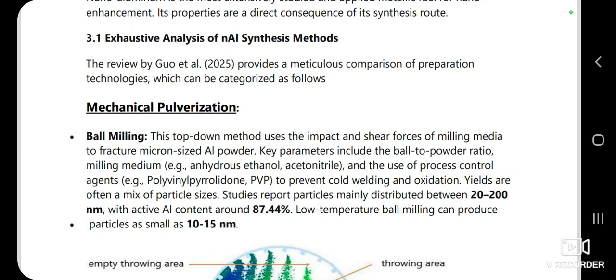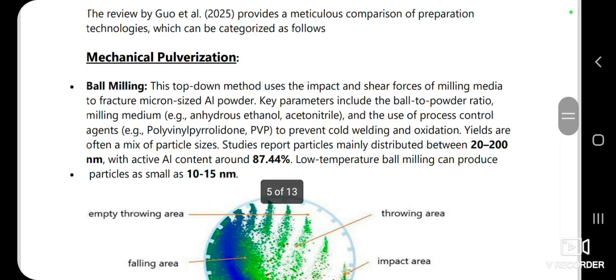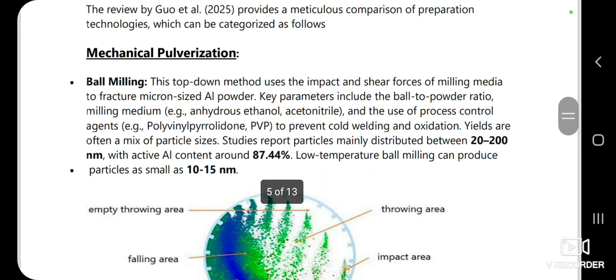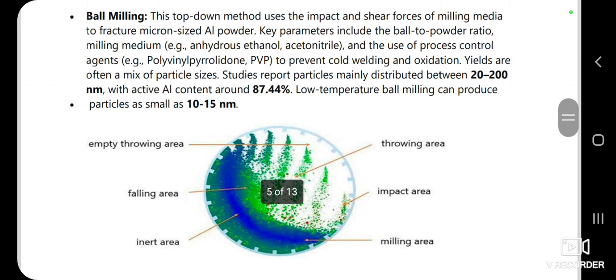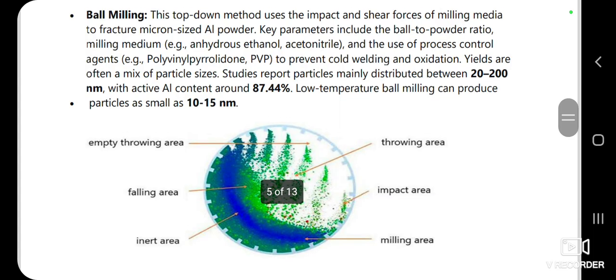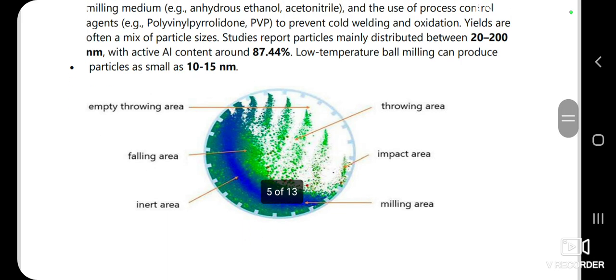Look at this comparison of the methods of formation of nanoaluminium. The first is mechanical pulverization, in which we use ball milling. The ball milling method is also known as the top-down method, and imagine taking some aluminium chunks and smashing them with nano sledgehammers. It's effective, producing particles from 20 to 200 nanometers, but mainly gives a mix of sizes, with active aluminium content around 87.44%. Low temperature ball milling can produce particles as small as 10 to 15 nanometers.